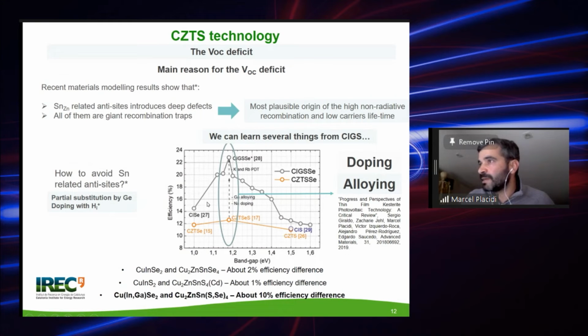And in fact, for chalcopyrite, it was demonstrated in the past, because for many years the efficiency was not increasing either. But at the end of the 80s, beginning of the 90s, they started introducing gallium in the chalcopyrite and also introducing alkalis, and they achieved very high efficiencies. So we strongly believe also for kesterite that the key could be optimizing doping and alloying, by finding the best possible materials.